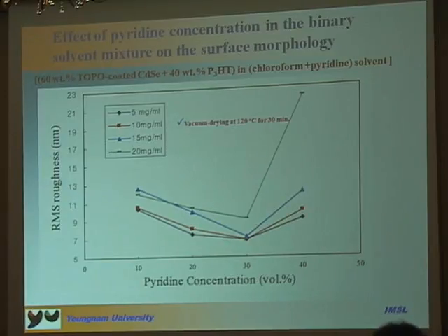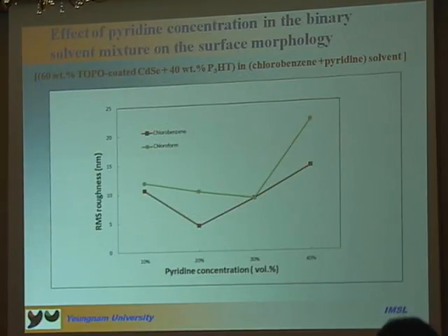Why do we get very high roughness with more than 30% pyridine in the solvent? Because P3HT is insoluble in pyridine. So if we put more than 30% pyridine in the solvent, at that time P3HT will precipitate. So that's why we use pyridine in the solvent at less than 30%. We also investigated by AFM the case of chloroform and chlorobenzene with pyridine.